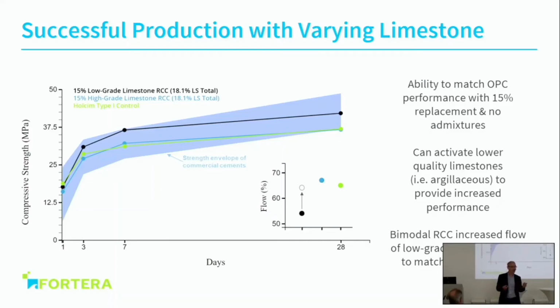In fact, it was to our surprise, but we should have anticipated it, because inside this low-grade limestone there was some clay, and by calcining, there was a pozzolanic effect from the calcining of the clay. What you see in blue is the envelope of commercial cements we have tested in the USA.